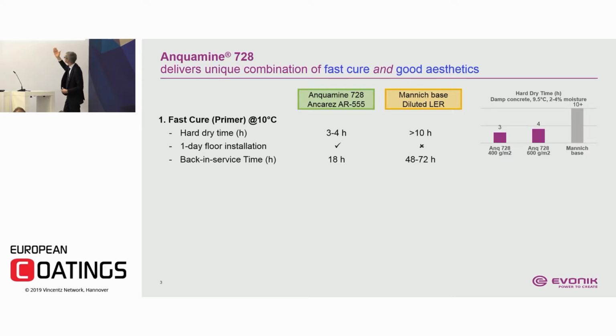With the amine-based system, and typically if you want to have an emission compliance system, you talk about slower curing systems in top coats. 2 to 3 days is not an unconventional return to service, and then you get this kind of comparison. So it makes quite a difference if you have a fast cure primer versus a normal primer.